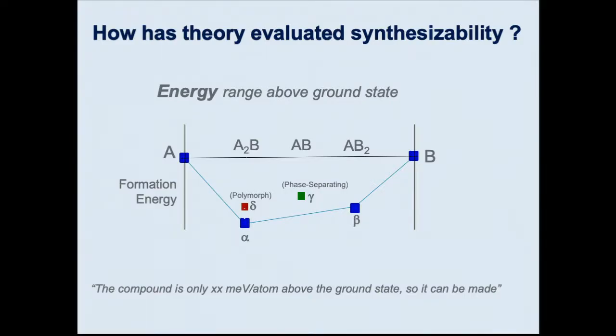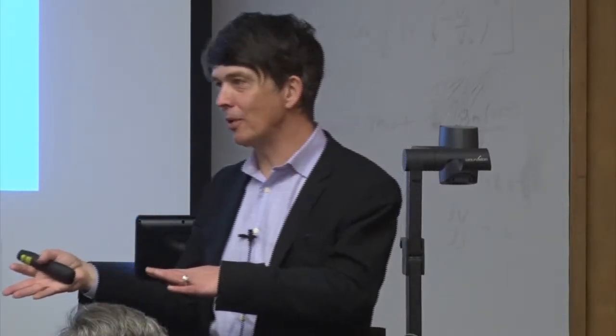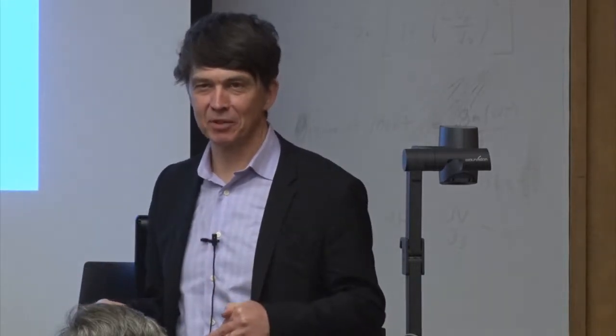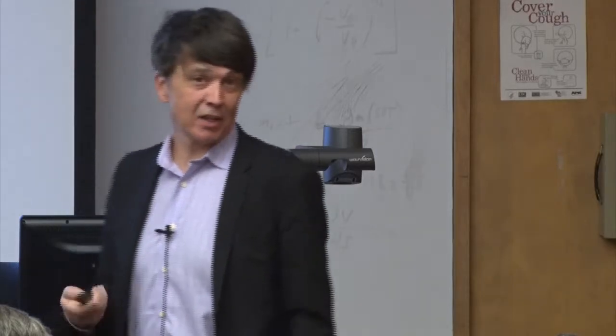So if you read any theory paper from the last 30 years in which they calculate new phases, they will usually tell you it's so much above the hull, or it's on the hull. And what's a good number for synthesizability? That depends on how optimistic you are, right? Some people say, oh, it's 50 meV per atom above the hull, some clever chemist will make it. They never say who the clever chemist is, right? Some people say it's 100 meV, you could still make it, right? So the question is, is there actually an energy scale of metastability?